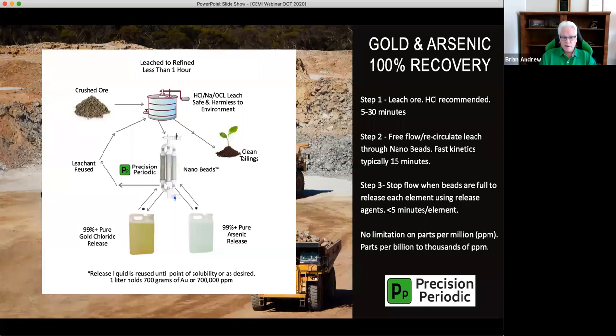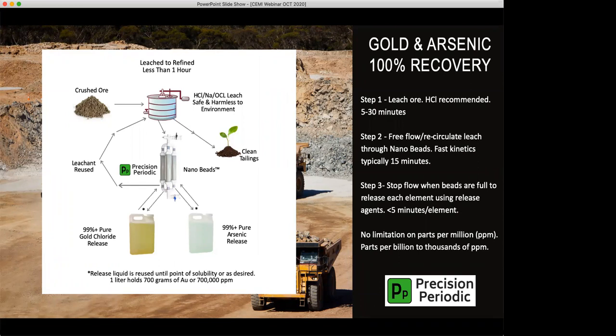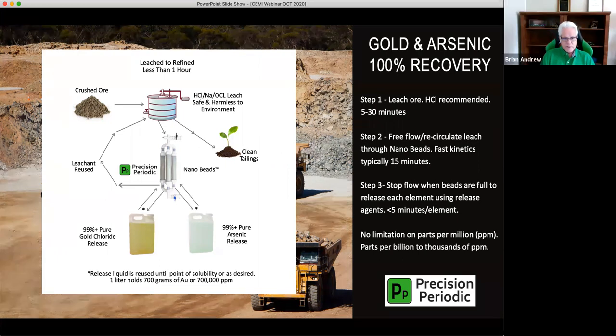So very fast, very efficient, and you produce, in this case, pure gold chloride. But the leaching technology is not unique to us. The filter beads allow us, or any of your hydrometallurgists out there, to select a more appropriate leachant to get the results you want without having to use a pollutant. For example, we have some folks looking at bromide or iodine. We can use sulfuric, we can use HCl, or whatever's necessary to get your metals liberated from the ore. And then from then on, we basically just take out the metals of interest.